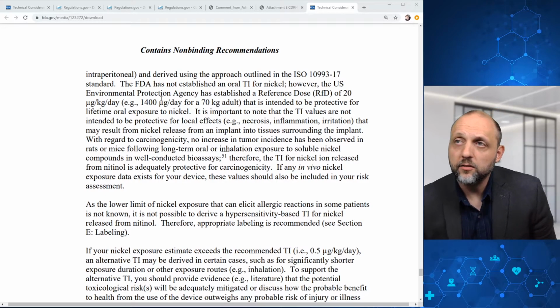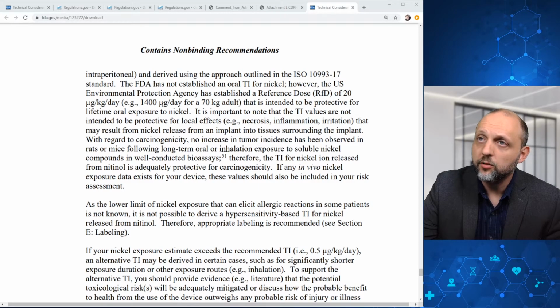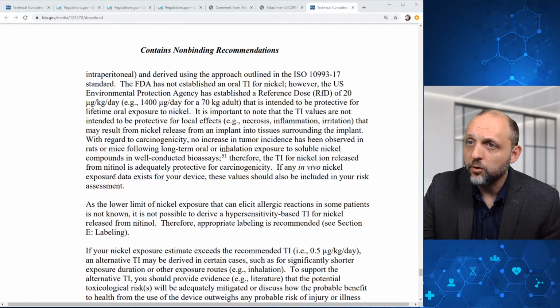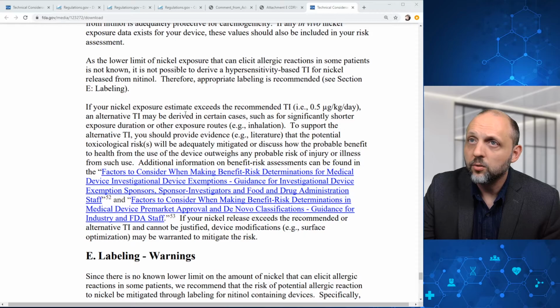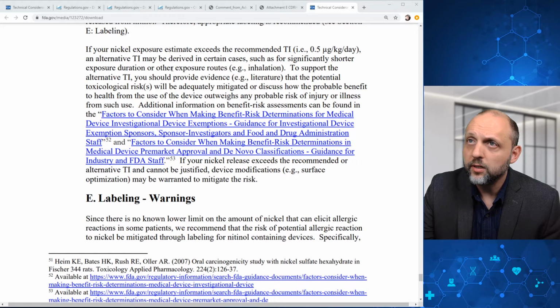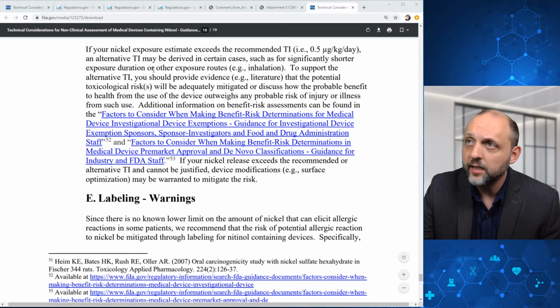And here, the FDA has not established an oral tolerable intake for nickel. However, the U.S. Environmental Protection Agency has established a reference dose here. And if any in vivo nickel exposure data exists for your device, these values should also be included in your risk assessment. As the lower limit of nickel exposure that can elicit allergic reactions in some patients is not known, it's not possible to derive a hypersensitivity based tolerable intake for nickel released from nitinol. Therefore, appropriate labeling is recommended. And if your nickel exposure estimate exceeds the recommended tolerable intake, an alternative tolerable intake may be derived in certain cases. And here, FDA provides some additional links.